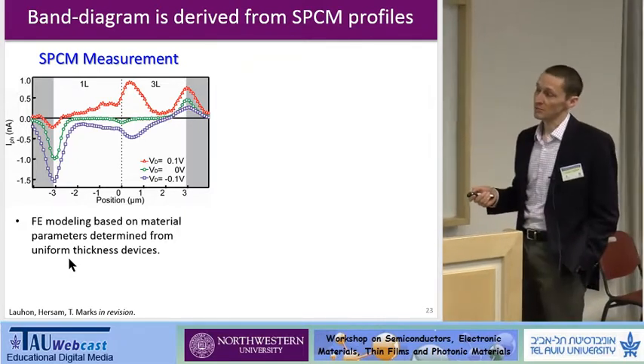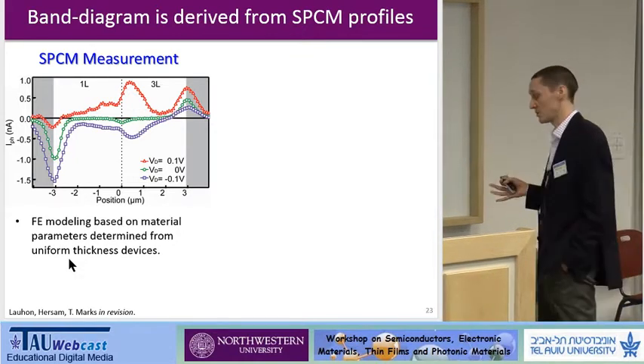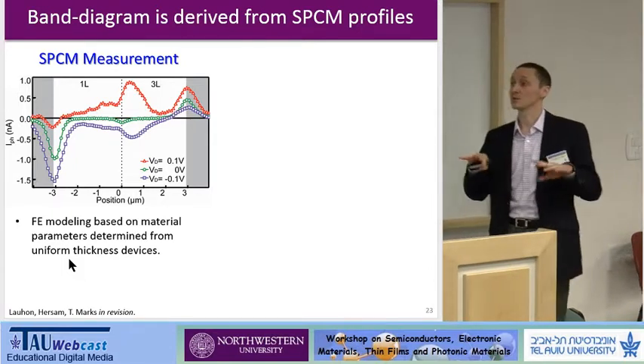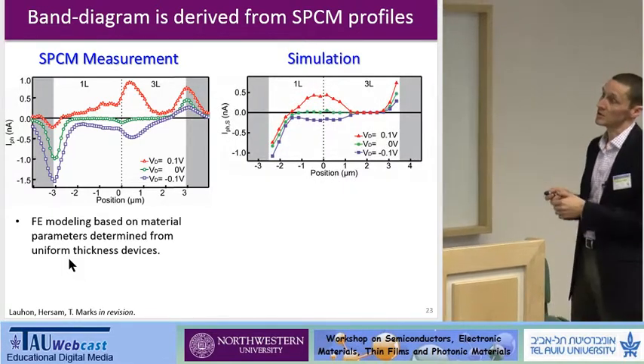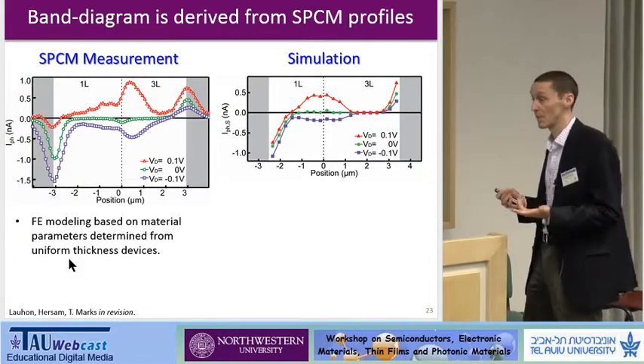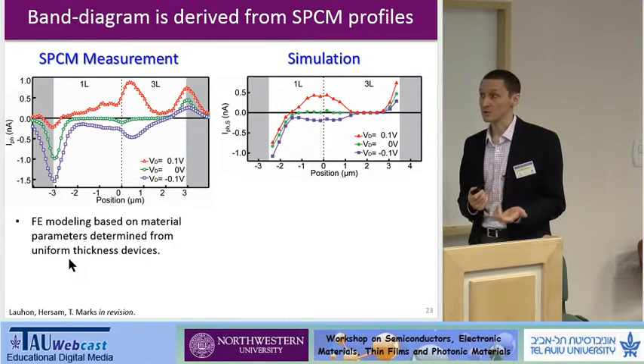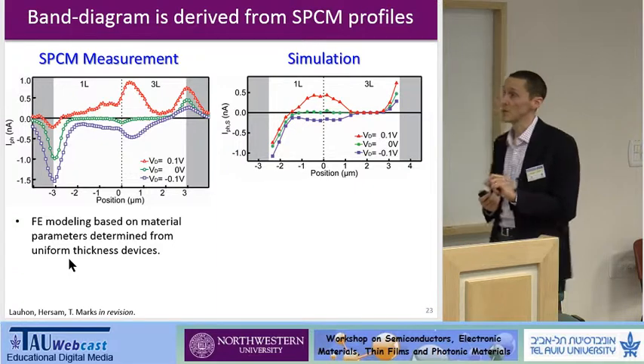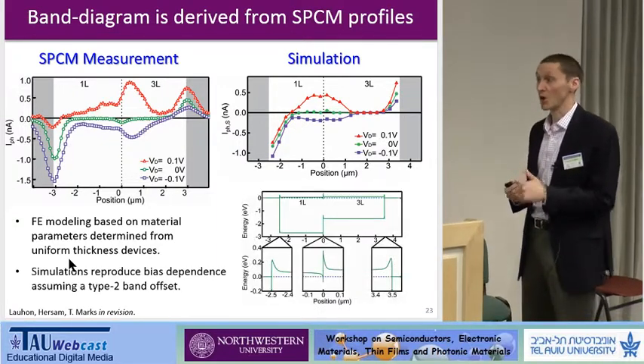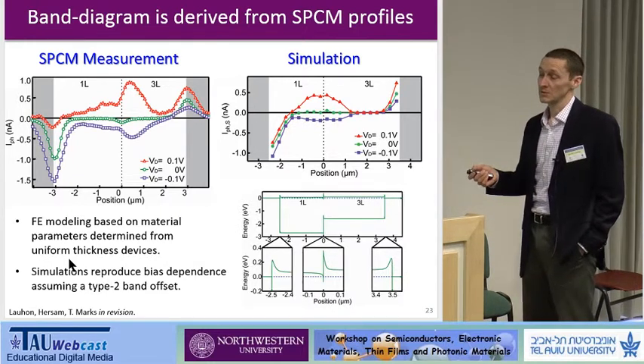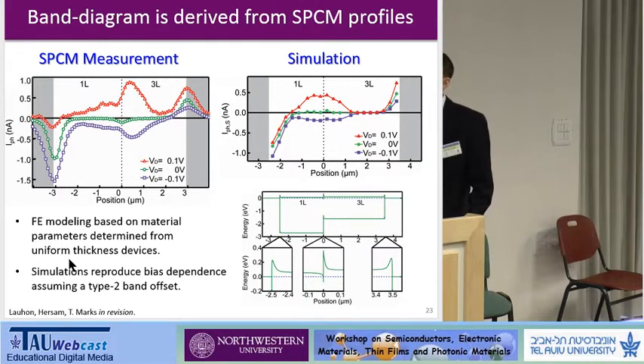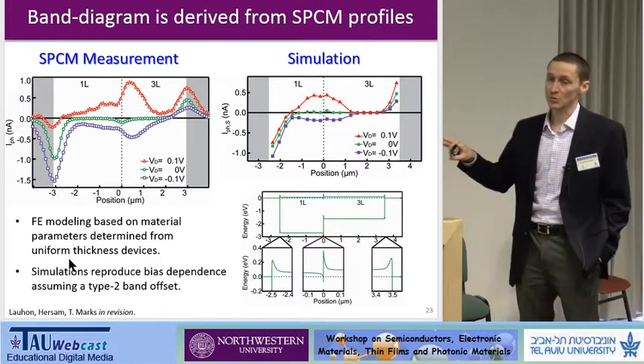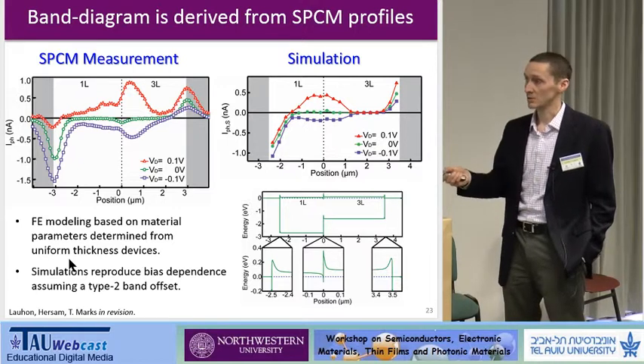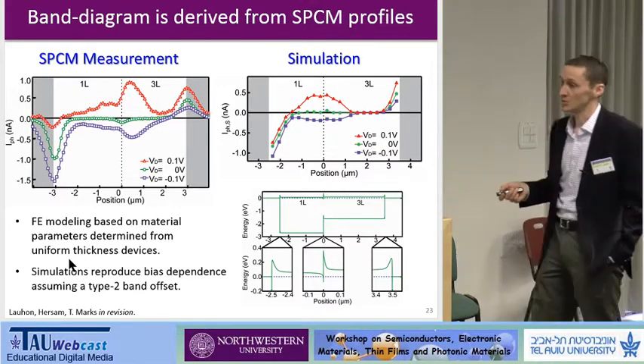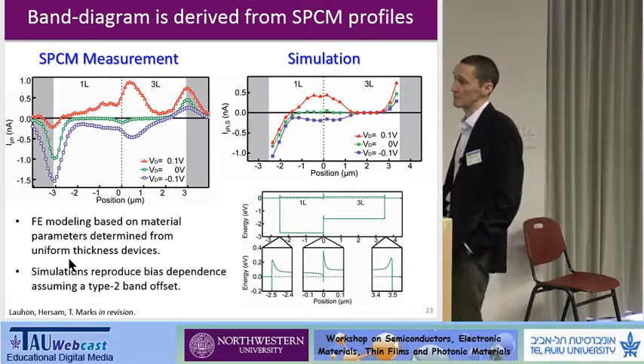Okay. And we did some finite element device modeling based on materials parameters that were extracted from devices of uniform thickness. So we use that as input, and just to summarize, in a device simulation, we're able to reproduce, at least qualitatively, and I would say semi-quantitatively, the local response of this junction to the photocurrent. What comes out of this simulation, or what underlies it, is actually a band structure. So we're using basic materials parameters, computing band alignment, we're able to reproduce the photocurrent map, but then also the rectification characteristics. So for us, this is a way, again, of using a local probe to try and reconstruct the band alignment at one of these novel heterojunctions. And this is something that's in revision at this point. We've been working hard to get it published.